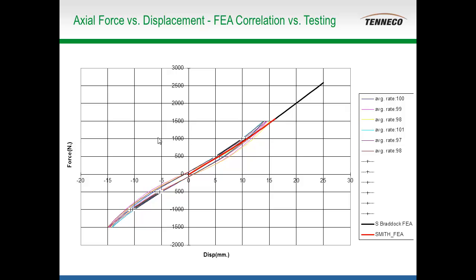But that's what gives us the best correlation, and it has really become the standard practice within Tenneco. This slide is just showing our results on one of the uniaxial directions that we did a fatigue test for. 6 pieces of part force displacement, and then the Abaqus predictions from 2 of our analysts. Very good agreement.